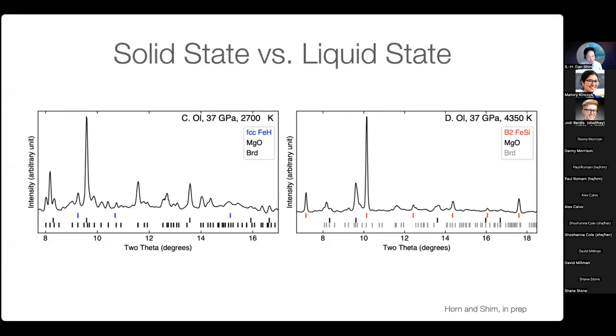Well, so far I'm talking about reaction in the molten state of silicate. We also conducted an experiment on the solid state of silicate. I'm just going to be brief and show you the results. The result we obtained is that silicon reduction is much more efficient in a liquid state. In other words, if silicate is in solid state or the temperature of the planet is low or cooled down enough, this reaction may be stopped or at least become really sluggish, so that the conversion from hydrogen to the water-rich planet will become quite inefficient. So the thermal history of the planets will be very important in this type of idea.